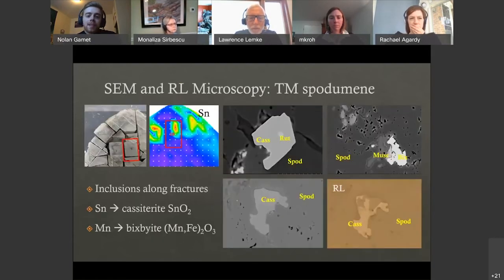So for SEM and reflected light microscopy of the TM spodumene, as seen in this section location, we located the inclusions along fractures. With SEM, we were able to identify these minerals as cassiterite, as seen in this SEM picture, and then bixbyite, which is a manganese iron oxide. And then also seen down here is a cassiterite crystal in reflected light and the cassiterite crystal in SEM.